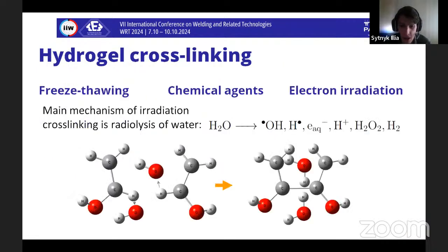After dissolving the polymers, they form a uniform solution, which has a consistency similar to that of sugar syrup. In order for hydrogel materials to be used as bandages, they need to be cross-linked. The most common methods of cross-linking polymer gels are cyclic freezing and thawing of materials, use of cross-linking agents, chemical agents such as boric acid, epichlorohydrin, glyceraldehyde, and electron beam irradiation.